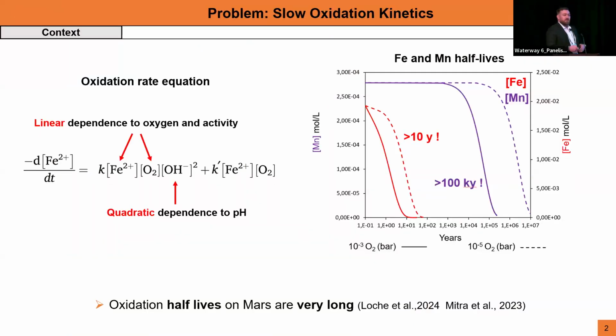The issue with Mars, and especially early Mars, is that you have this thick CO2 atmosphere. And when you equilibrate CO2 with water, you're going to have a rather low pH. And because the dependence of the oxidation rate on pH is more important than the one on oxygen, it's going to hinder your oxidation speed even more.